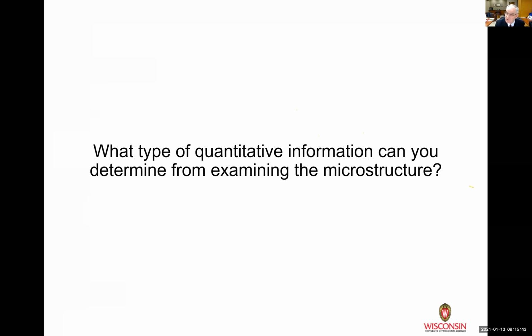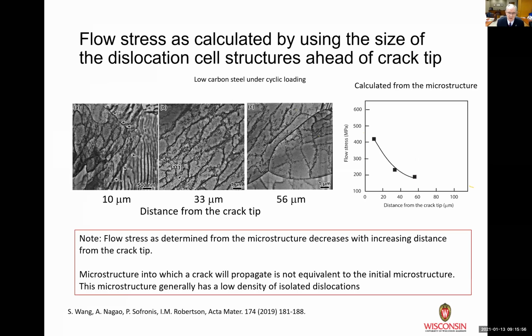I can actually derive more information that I can then relate back to the macroscopic stress strain properties than I used to be able to do in 1984. So what kind of information can you get? Well, here's just an example. This happens to be a low carbon steel that was deformed under cyclic loading. And in this case, the macroscopic specimen, we stopped the loading before the crack had propagated all the way through. So it's an arrested crack.